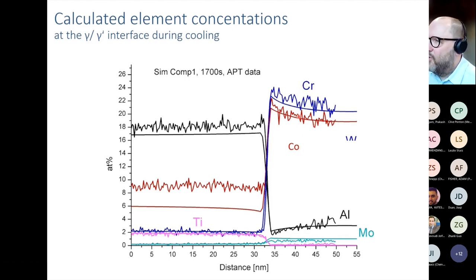So here, chromium and cobalt inside the gamma phase are spot on. Aluminium is very good. Moly is quite good. There's some discrepancy for cobalt inside the gamma prime phase, but having spoken to the people who have done the 3D atom probe, they said, yeah, but cobalt's a bit difficult to detect sometimes, so that could actually be an error in the detection as well.